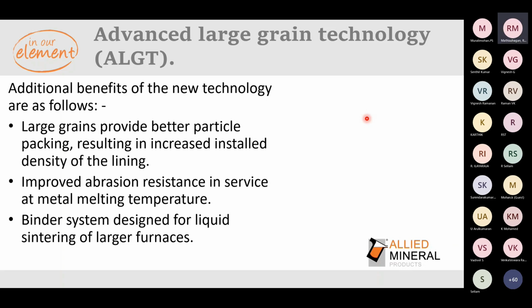This product has been designed for liquid sintering, and because of the grain sizing and grain distribution we have, it has improved abrasion resistance, especially in areas like the taper section or cone sections where you find a lot of elephant foot erosion.